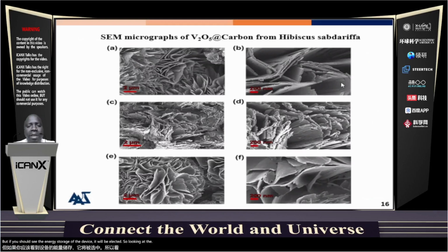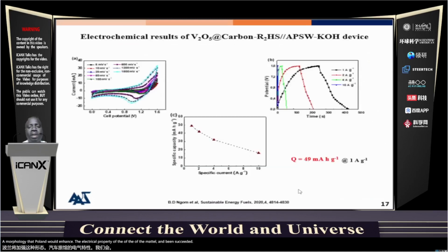So looking at the SEM, A, B, C, and D, the high magnification, which has A, C, and E, and the low magnification at 200 nanometer, which is B, D, and F, are showing the different morphology that we have when we move from one hibiscus, the white one, the light red and the dark red one. And you could see that we are having a 2D material, which could be one of the morphologies that could enhance the electrical property of the material.